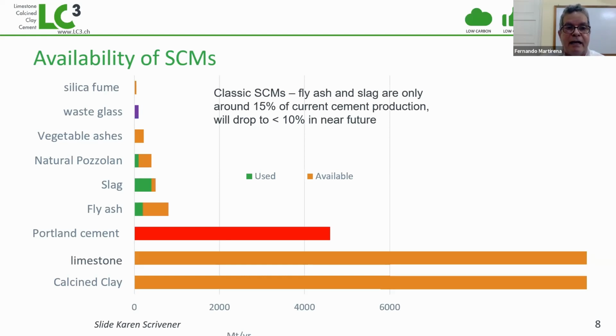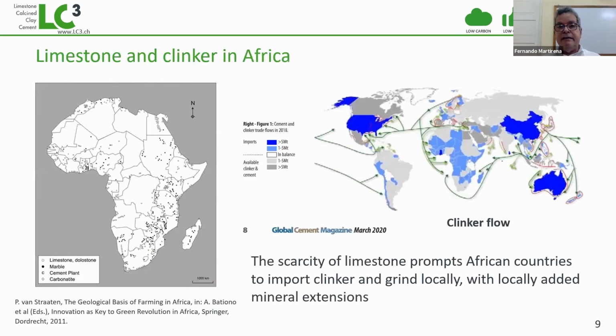For instance, slag and fly ash, which are the most commonly used supplementary cementitious materials, you see their availability would be something like, I mean, the highest would be 15%. And even in the case of fly ash, we're using only a small part of the fly ash produced in the world in coal power plants. Therefore, the only materials that are widely available and that could be suitable supplementary cementitious materials are limestone and calcined clay.